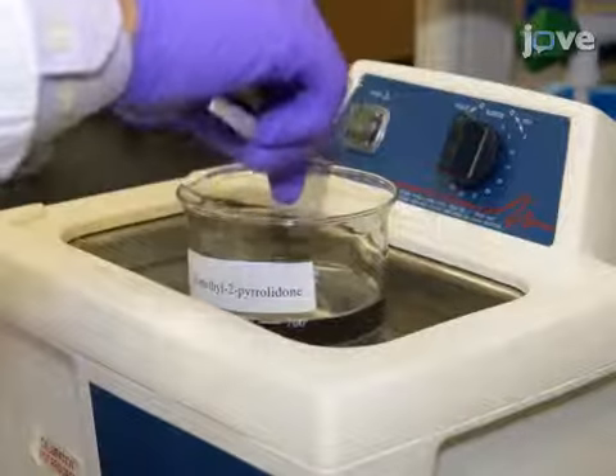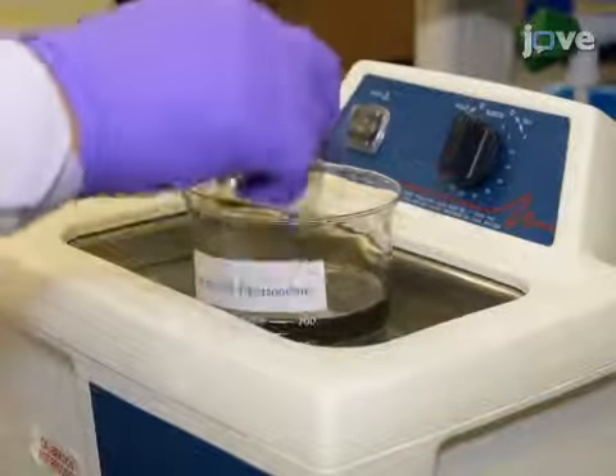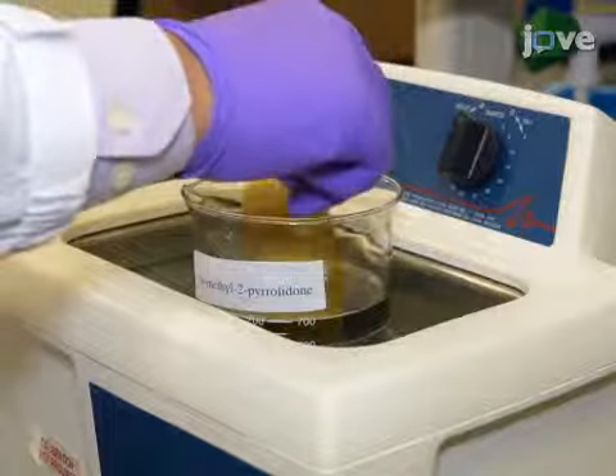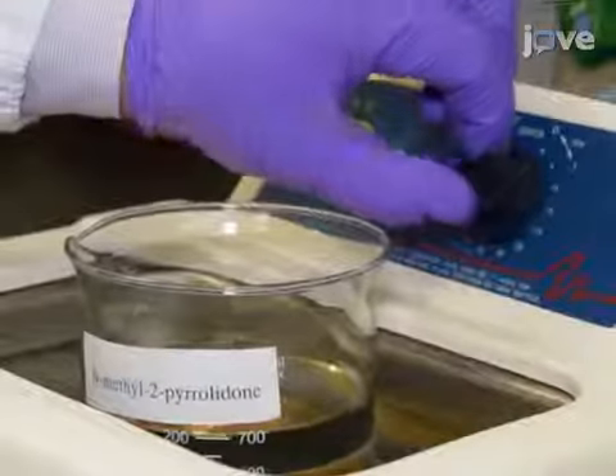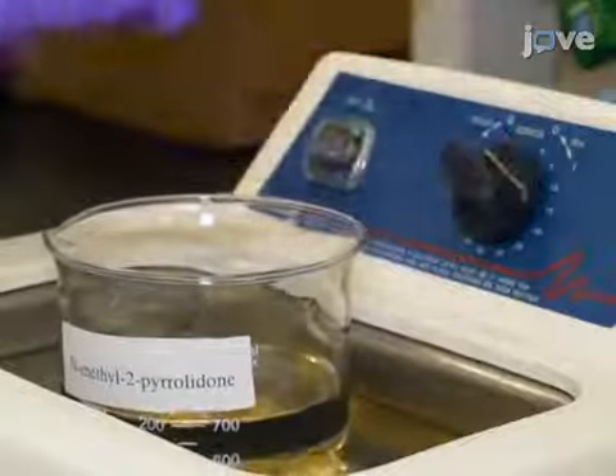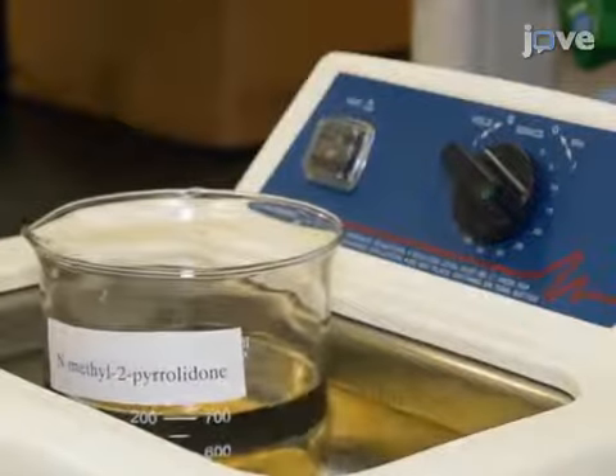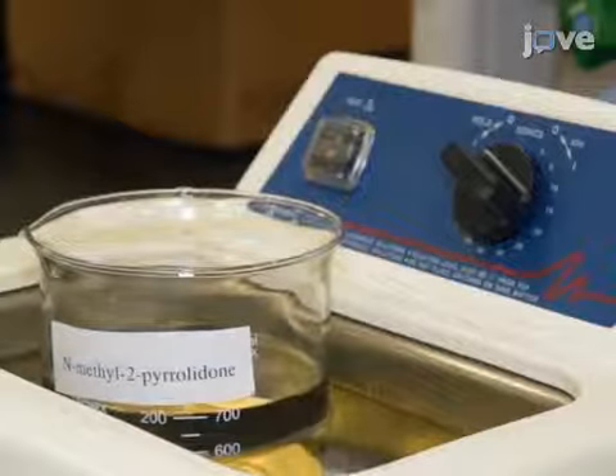Place the glass wafer into an ultrasonic tank containing N-methyl-2-pyrrolidone at 80 degrees Celsius and use ultrasonication for 1 hour to remove the remaining wax, the photoresist, and the overhanging chromium and gold layers at the edges of the lenses.